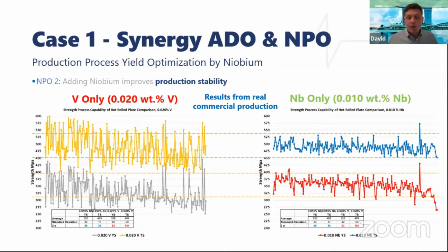As you can see, the niobium ones, because of the improved balance of grain refining and precipitation hardening, better than the vanadium that is strongly dependent on precipitation hardening, the niobium can manage to achieve more stable results, generating much less downgrades or even discard of a product due to variation of the mechanical properties. Therefore, overall in a year, this is cost reduction. So smaller variation or production stability can be translated into cost.